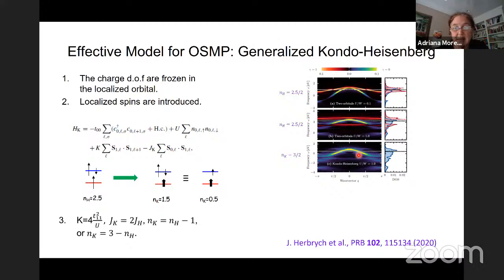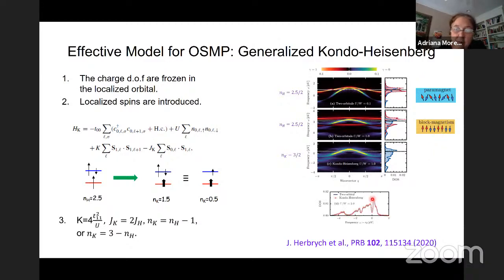In addition, notice that this is very different from a free particle. I forgot to say that this was the paramagnetic case, and this is the block magnetic situation. So here, this is superimposing the metallic part of this model with the result for the Kondo model, and you see the excellent agreement that we obtain between the two models.